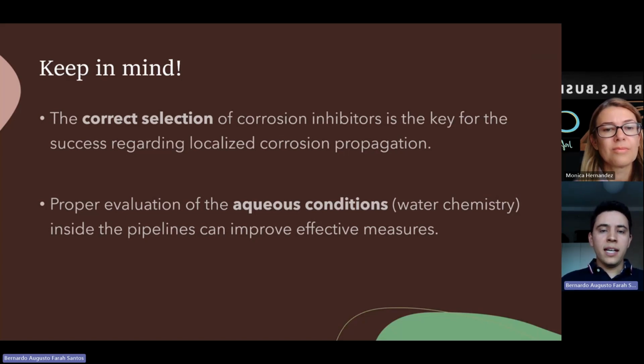So when you see that, depending on the application you're having, in this case, you have a shift in potential. You want to overcome that shift in potential. Maybe, I'm not 100% sure because we haven't tested that, but there is a strong potential that you may not be able to stifle that mechanism, even though the inhibitor might be absorbing on the surface. But that goes back to the fact that, depending on the condition, the inhibitor would not even absorb to the surface. So making the correct selection of corrosion inhibitors is really important.